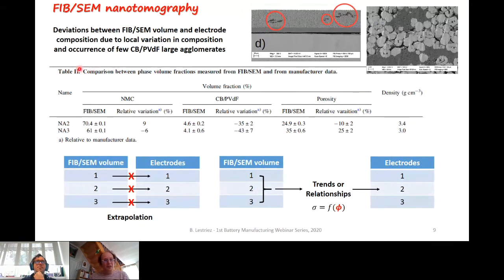So these deviations can be illustrated by looking at this table. For example, these two electrodes, Na2 and Na3, have the same overall volumetric composition at the macro scale, and they have, for example, 65% of NMC. You see that the Na2 electrode is richer in NMC, while the Na3 is poorer in NMC than the macro scale composition. The counterpart is that the Na2 electrode has a lower porosity than at the macro scale, which is 28%, while the Na3 has a higher porosity. Whatever the FIB-SEM volumes, we observed that the CB-PVDF content is 20 to 50% lower than the overall composition, which can be attributed to the occurrence, as you see on this large cross-section, of very large CB-PVDF agglomerates, which suggests that the manufacture of the electrodes was not fully optimized.